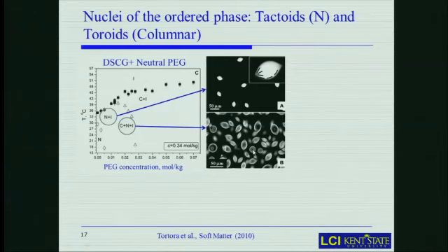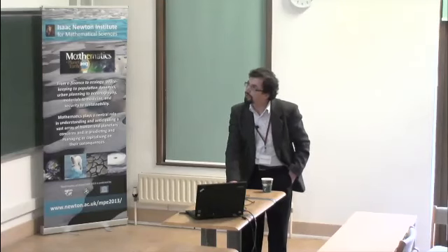Here in the center you have the isotropic phase, so it's like a little toroid that is floating in the isotropic phase, and it's happy because the director is tangential to the interface, and the only type of distortions that you have here are distortions of bend. There is no splay, so apparently the aggregates are becoming very long or infinitely long, and they're just circulating around this hole in the toroidal nuclei.